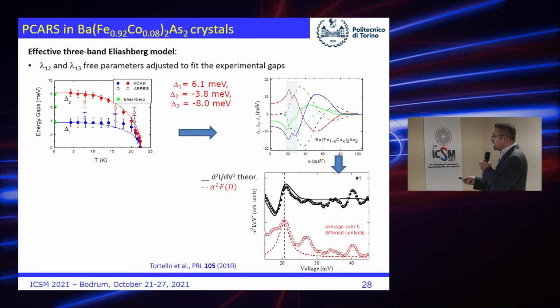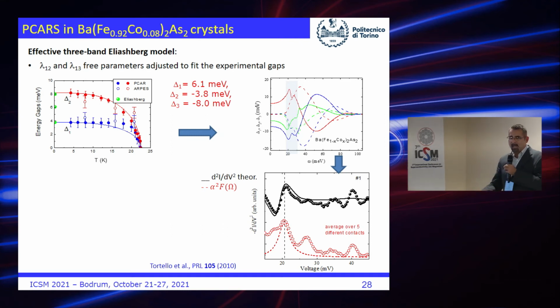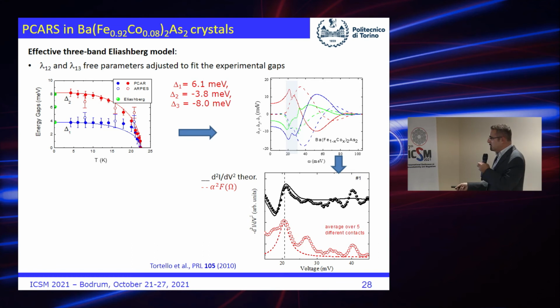So I calculate the values of the gap here. These are the functions of the gaps, so real and imaginary part for all the 3 bands. I calculated the spectra, I calculate the second derivative, I obtain that the points are the second derivative of the experimental curve. The line is the second derivative of the theoretical curve. So there is a very good agreement.